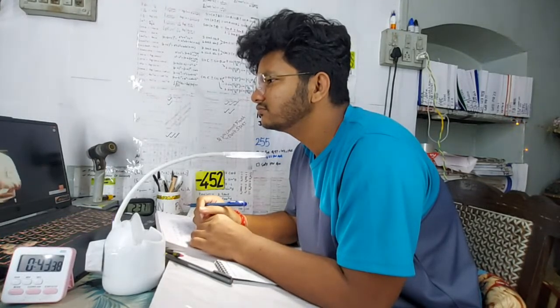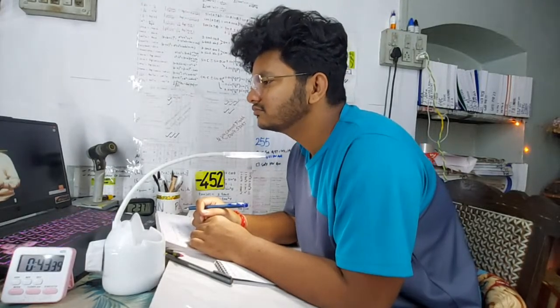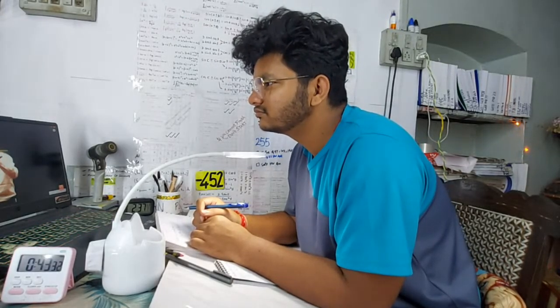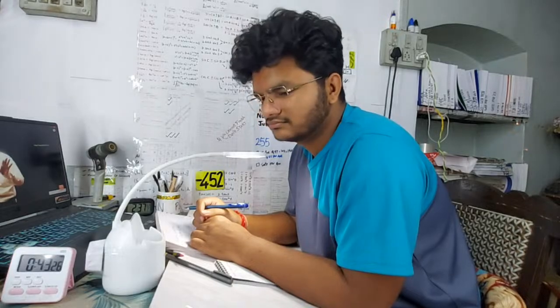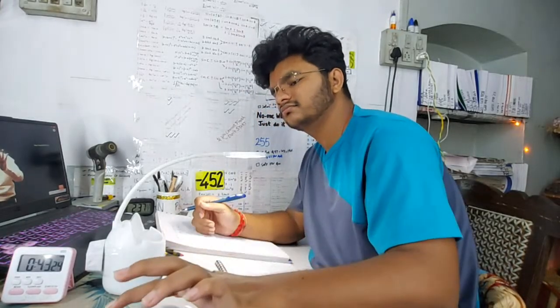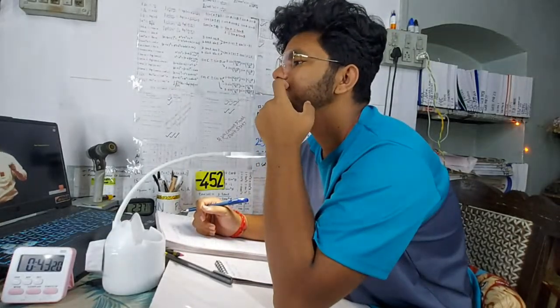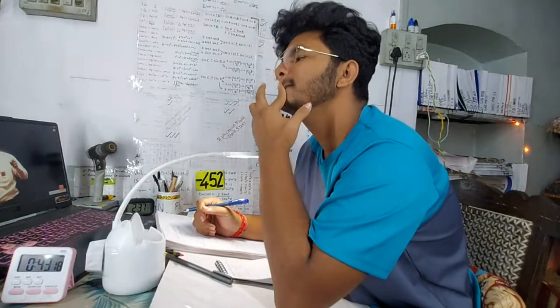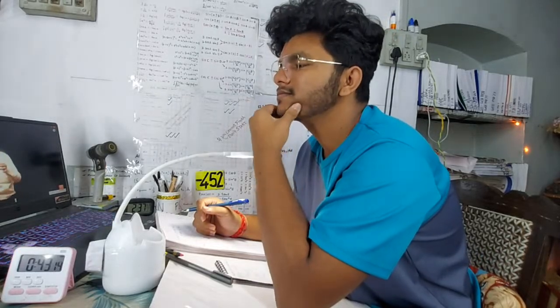B1 is the beginning time for formation of pearlite from austenite. It is not 0. What is the importance of 0 seconds? At 0 seconds you did rapid cooling and started holding at constant temperature, and at B1 seconds the transformation began. Now the time which has elapsed between 0 seconds and B1 seconds is called the incubation time.